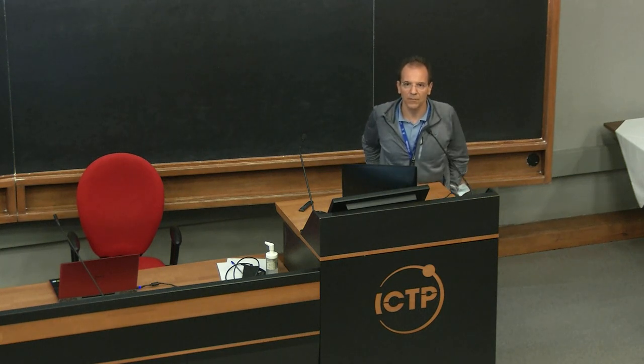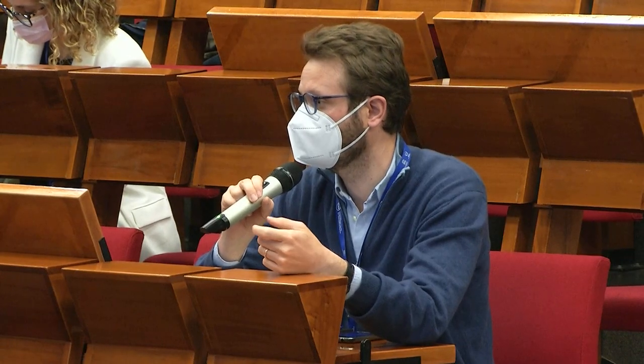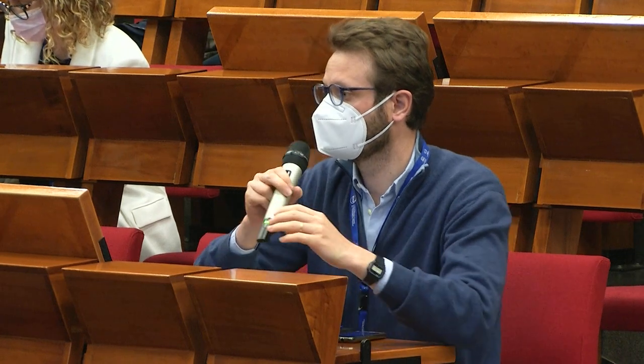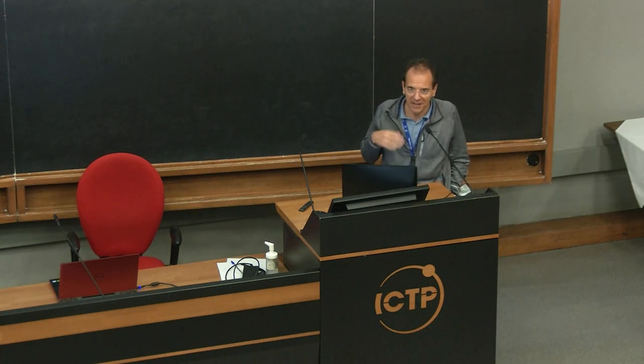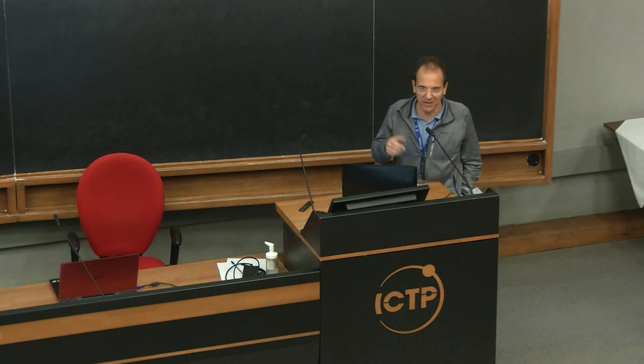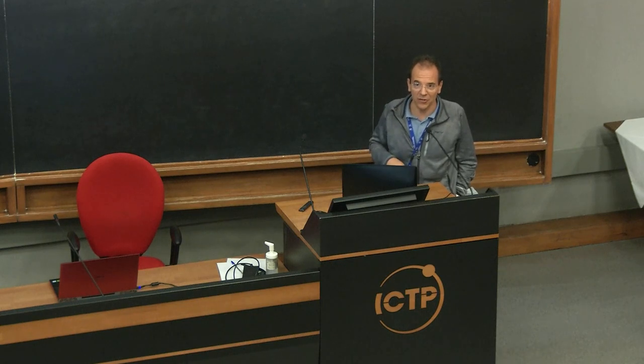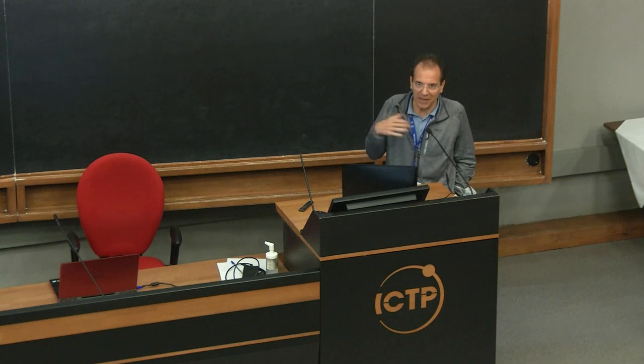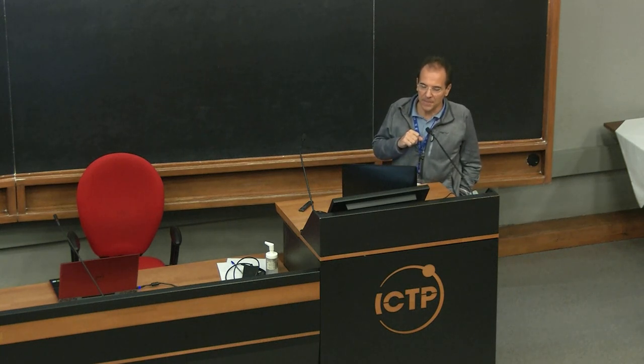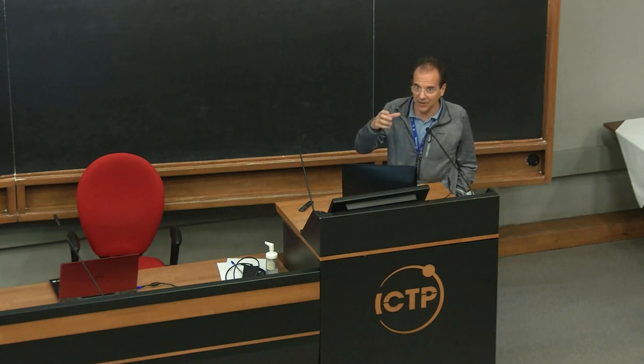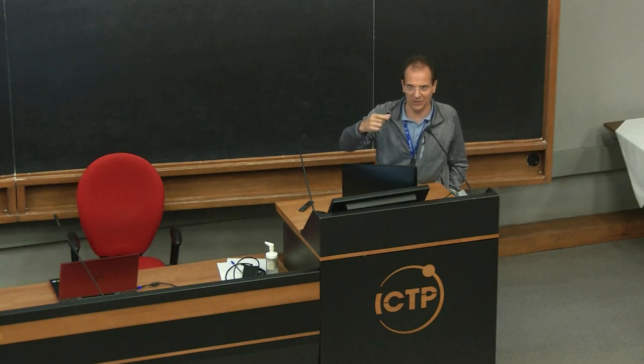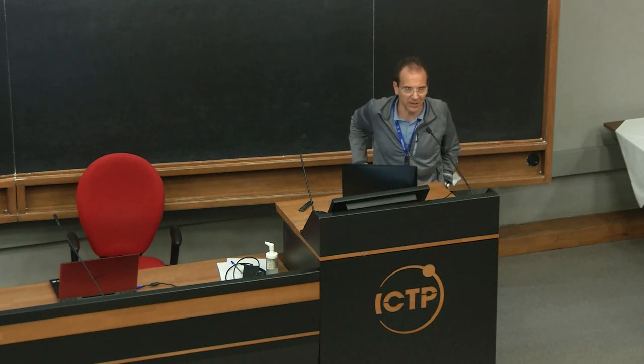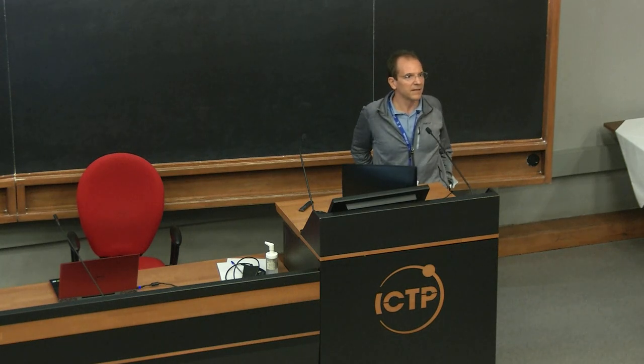Solvent there. In particular, I think about water, but also salty water, because then you can maybe form ion bridges or something like that. In principle, of course we have considered it, because in experiments they do have a solvent. We wanted to make a minimal model at the beginning, and so we did it without any solvent. But certainly, the next step is to include a specific solvent and also include salts, as you say, and see how that will change things. In our modeling without solvent, just to make it somehow quicker and easier, we somehow tuned the interaction between the residues. This interaction range takes into account the possibility that there are molecules in between. So it is bigger than atomic interaction, like 0.4 nanometers instead of 0.1.